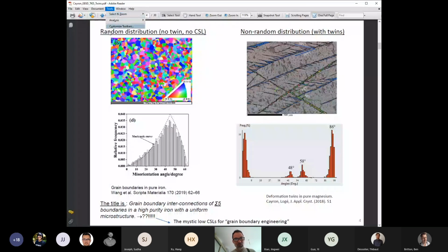Okay, so when it is random, the distribution of grains, the misorientation between the grains, should follow more or less the Mackenzie curve that is here. And this Mackenzie curve you can compute. You take two cubic grains randomly orientated, and you take into account the cubic symmetries, and you will realize that the distribution of rotation angles is not homogeneous. It follows this curve, Mackenzie.